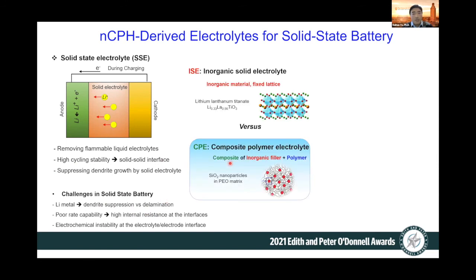Conventionally, there are two types of materials for a solid state electrolyte, the key component of solid state batteries. One is called inorganic solid electrolyte, which is typically ceramic material, for example, lithium lanthanum titanate, LLTO. To have better handleability, because ceramic is typically more fragile, people are trying to explore composite polymer electrolytes, which are a composite of both inorganic ceramic filler, with better ionic conductivity, and ionically conductive polymers. So with this composite, even with a little bit lower ionic conductivity, you can make the interface more intimate to make a higher rate possible.